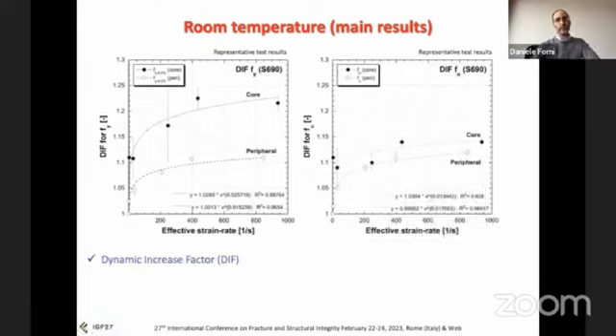The strain rate sensitivity is also well represented in these plots, where the dynamic increase factor, as the ratio between the quasi-static to the dynamic mechanical properties, is depicted. On the left, this ratio is reported for the yield, while on the right is depicted for the ultimate tensile strength, highlighting the different strain rate sensitivity of core and peripheral zones.